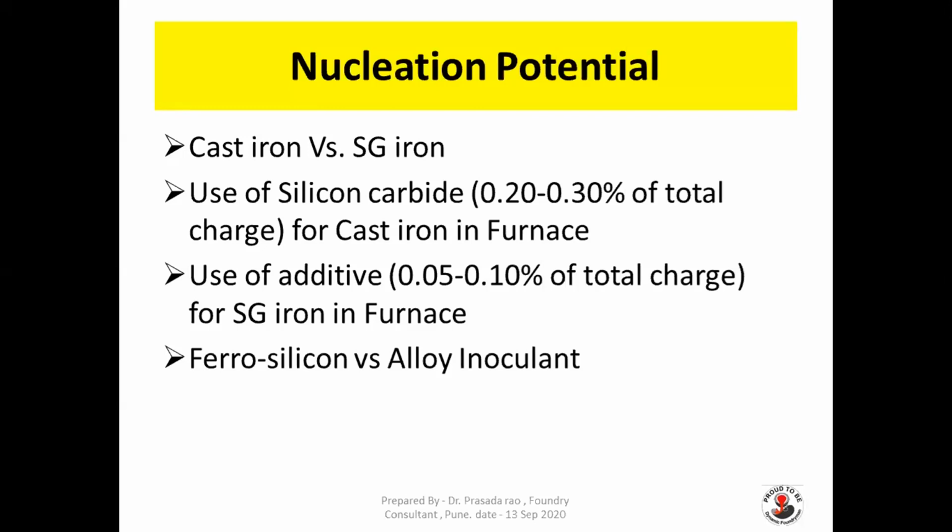Please remember one point very carefully. Ferrosilicon melts in the furnace. Silicon carbide dissolves in the furnace metal. This is the basic difference one should always keep in mind. Then people will understand how to use it.